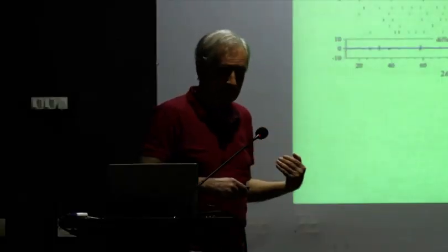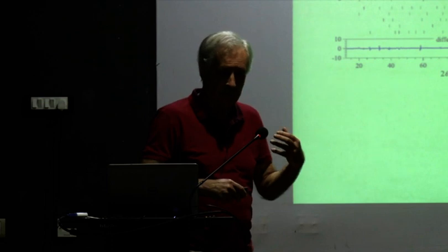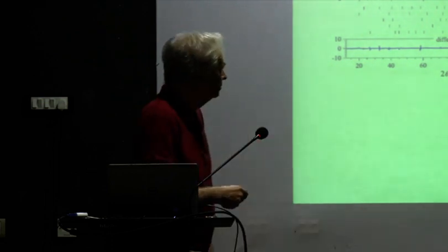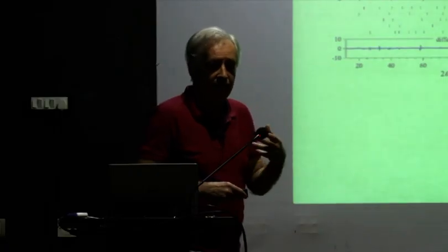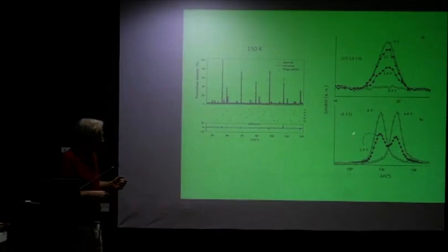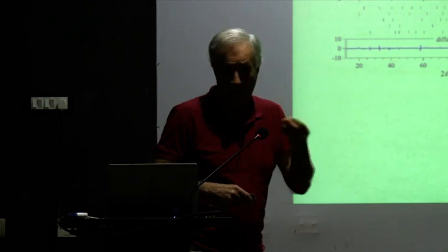Now, Mn3GaC has a high volume, low temperature state. That is in the antiferromagnetic state. Its volume is larger than in the ferromagnetic state, and it has a volume anomaly. This peak will give us information on how the magnetism is changing when we're applying a field. And this complex structure over here will give us information on how the volume is changing eventually.